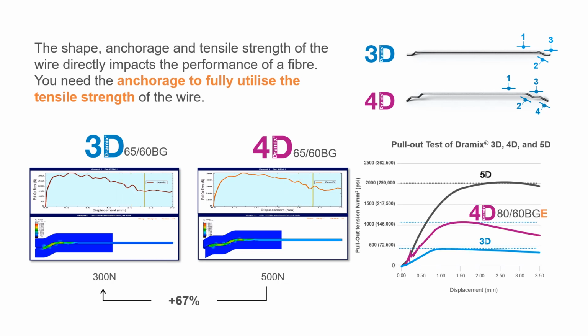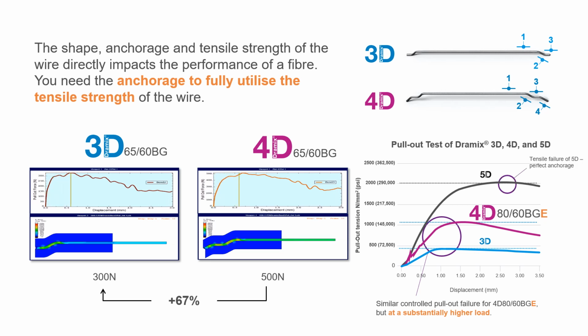The graph on the right hand side is of our 4D 8060 BGE fibre. It has a similar controlled pull-out failure, but at a substantially higher load. I'm also showing our 5D fibre, which is in a class of its own, as it's fully anchored into the concrete, and it is the ductility and tensile strength of the wire which gives us its performance.